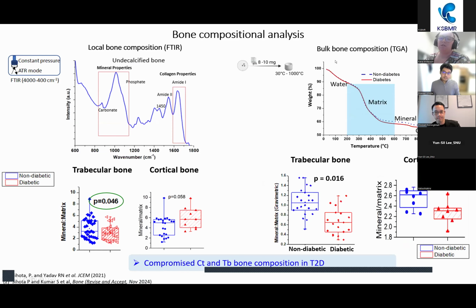And bulk bone composition is done with gravimetric analysis, where we heat the bone and measure the decomposition of the bone at different temperatures. It's a really quantitative approach. And here we found that the mineral to matrix ratio for both trabecular and cortical bone is lower in the diabetes group.